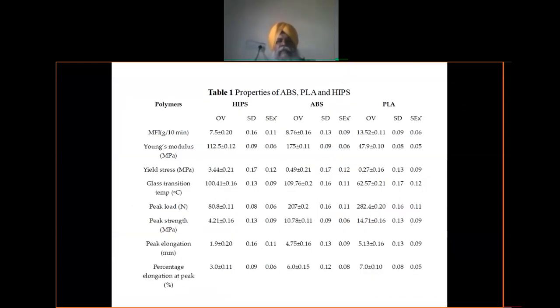So what we actually did is we selected three different types of polymers. One is HIPS, another was ABS, and another was PLA. The difference is, HIPS was having an MFI in the range of 7.5, ABS was having an MFI of 8.7, and PLA was having an MFI of 13.52. That means if I apply the same quantity of load under the same temperature condition, PLA is going to give a very thin section, whereas for HIPS, I need to produce the thick section only.